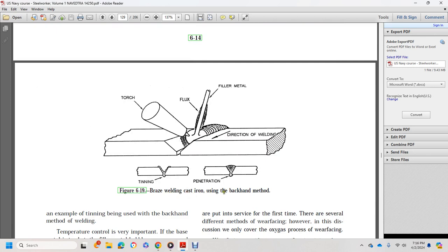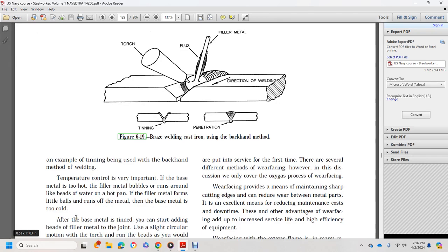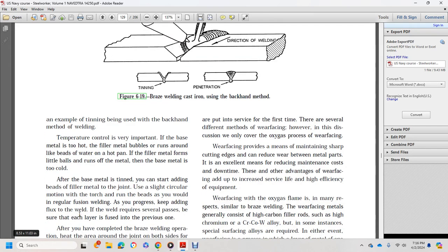the brazing of cast iron using the backhand method. It shows the torch, the flux, the filler metal, the direction of the weld, the tinning, and the penetration. This is an example of tinning with the backhand method. Welding temperature control is very important. If the base metal is too hot, the filler metal bubbles and runs around. If the filler metal forms a lifted bubble that runs off the metal, then the base metal is too cold.